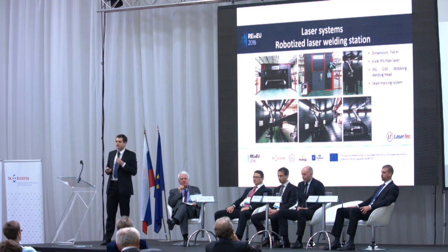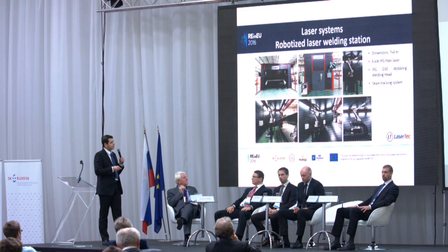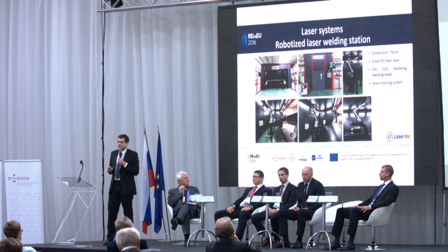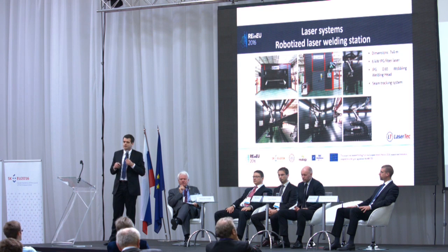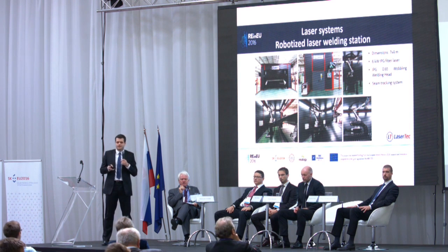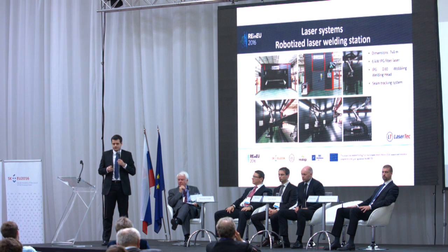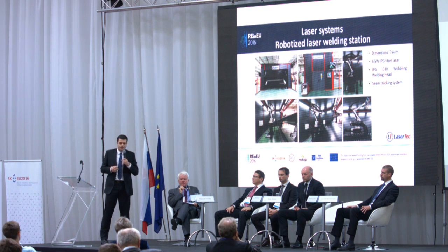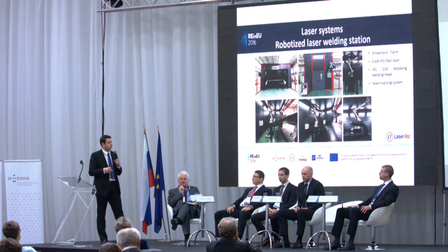We used a 6 kilowatt IPG laser for the laser beam welding process, and a head for welding called a wobbling welding head. This means that you can use motorized optics inside the head to wobble the beam around a circle. So basically you can adjust the diameter of the spot size for the welding process. So it's very flexible, because you do not have to change the optical components if you weld different parts and you need a different spot size. We have also used a seam tracking system in this application, so you can check the position of the joint in real time, and the robot program is corrected automatically.